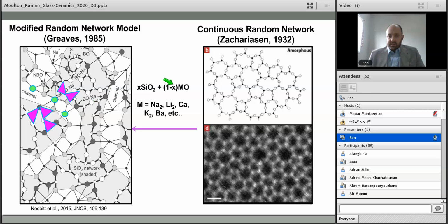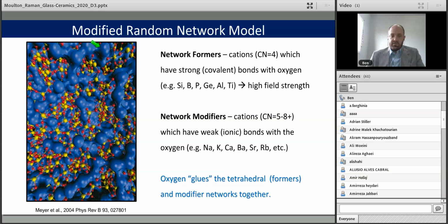Okay. So we have the silicate network. As we add modifier or metal oxides to this network, it breaks it up and you get regions where, for instance, sodium is concentrated. And these were described as channel structures. If you have just a bit, they might form sort of an island here, and as you add more, you might form these continuous channels through the network.